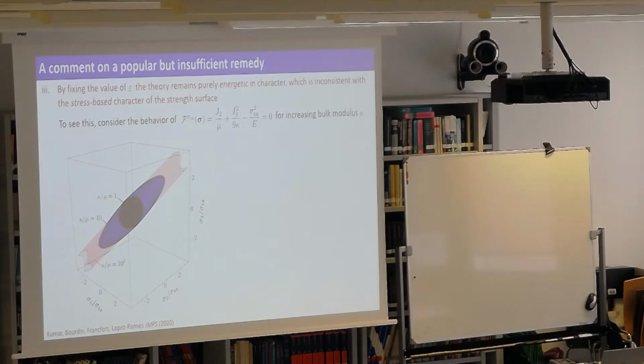If you fix everything and the only thing that you change is the bulk modulus of your elasticity, the surface, let me show you a cross section, right? Kappa is the bulk modulus. For kappa near mu, things are actually not that bad, right? That's reasonable. But when you start to increase kappa, you realize that the strength surface is doing something that is not physical. It's telling you that when you do hydrostatic tension, which is worse than uniaxial tension, the material gets stronger, right? That it will never break when you make it incompressible, right?